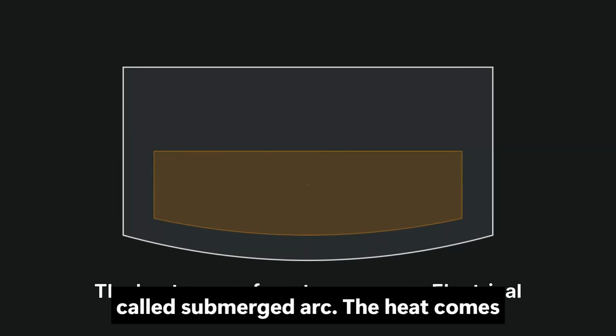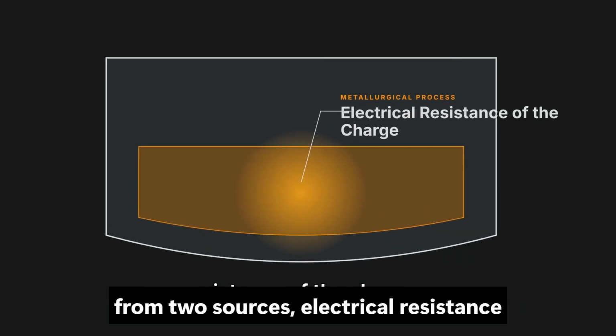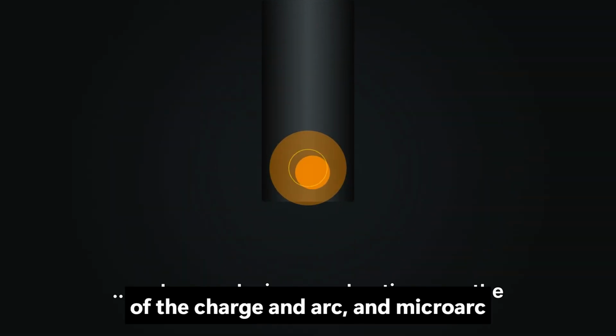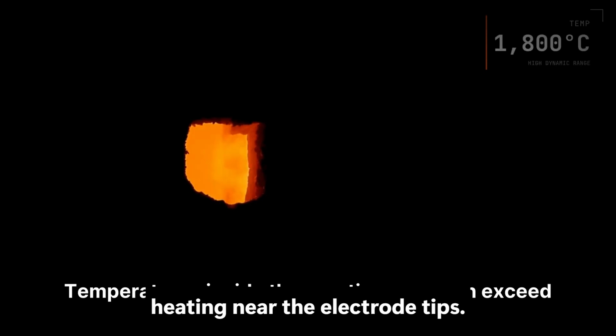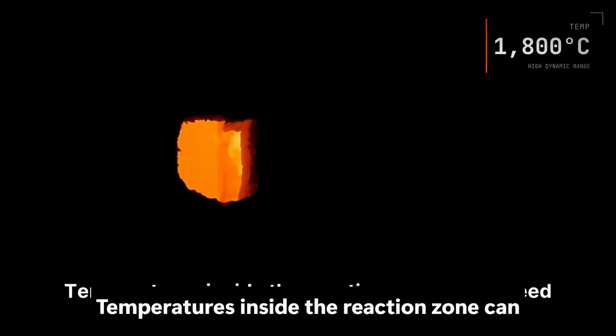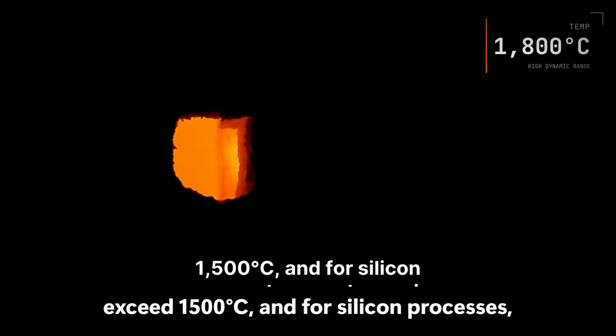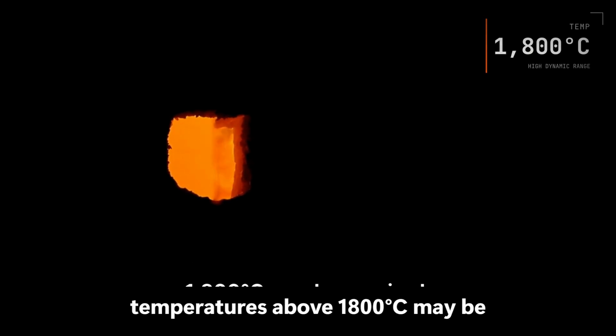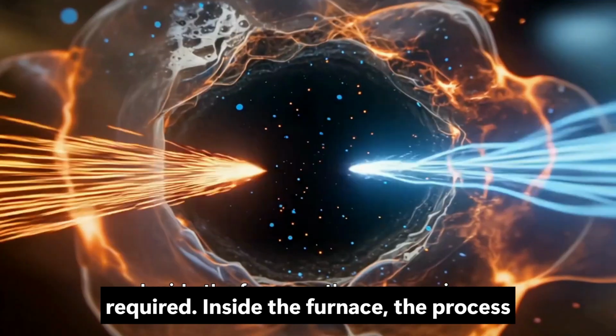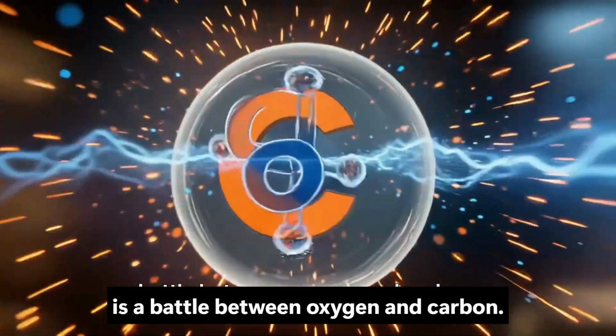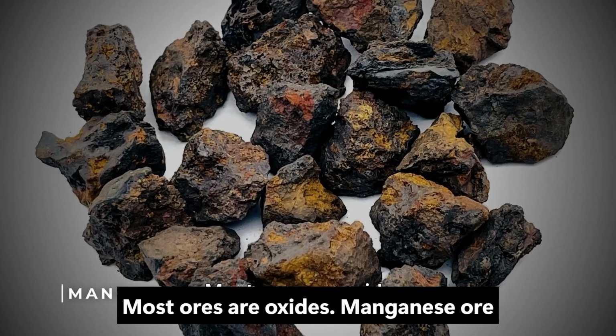The heat comes from two sources: electrical resistance of the charge, and arc and microarc heating near the electrode tips. Temperatures inside the reaction zone can exceed 1,500 degrees Celsius, and for silicon processes, temperatures above 1,800 degrees Celsius may be required. Inside the furnace, the process is a battle between oxygen and carbon. Most ores are oxides.